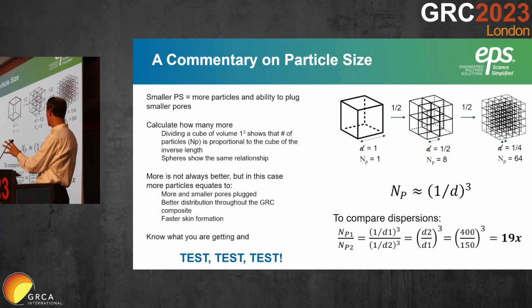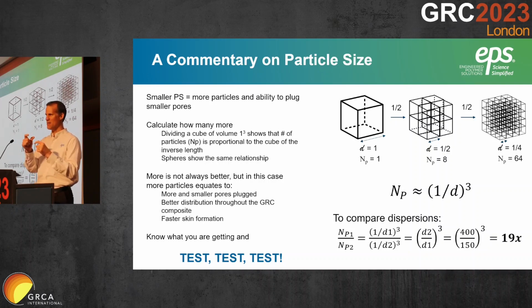In general, the number of particles is proportional to 1 over the diameter cubed. So if you have the primary particle size of a resin and you want to compare 2 different resins, you can essentially divide the diameters cubed, and that's the difference between the 2 of them. If you have a 400 nanometer particle and a 150 nanometer particle, you've got 19 times more particles with a 150 nanometer particle than with a 400 nanometer particle. So the difference in particle size isn't that big, but the difference in number of particles, and how well they're dispersed throughout, is significantly different.